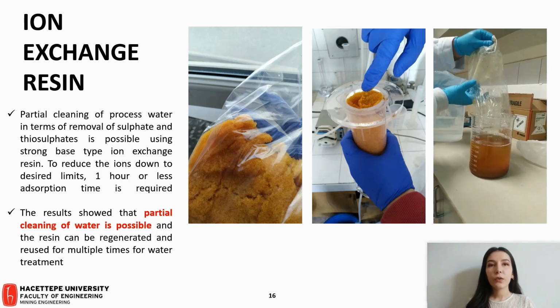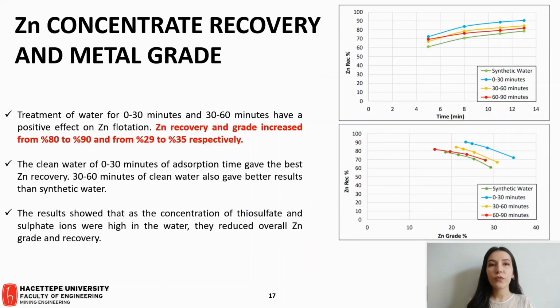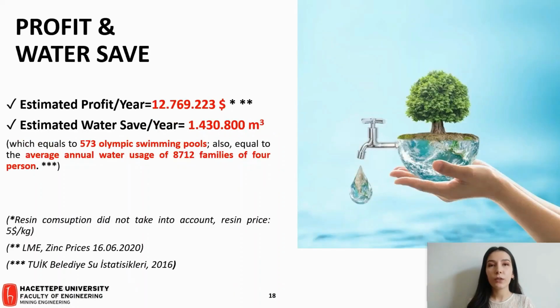The treated water was mixed with tap water in a ratio of 70 to 30%, and this mixed water was used for flotation tests. The results show that treatment of water has improved the zinc flotation process. The zinc concentrate recovery and metal grade increased from 80% to 90% and from 29% to 35% respectively. These figures are very promising in terms of money for the metal industry. After all these engineering applications, a significant amount of water and money was saved.